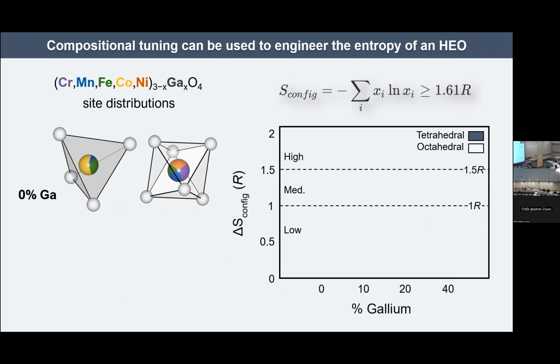So we can take data like that, analysis like that, and we can reconstruct on a site-by-site basis exactly what is the composition of our material. So instead of writing the structure like this, where I make no assumptions about those A and B sublattices, I can make this pictorial representation where the pie chart represents what fraction of that site is occupied by each of our 5 elements. And so this is the resulting composition for my 0% gallium material.